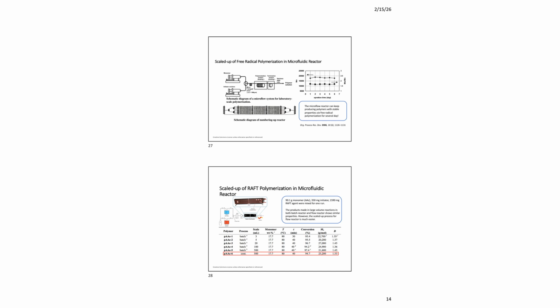This scalability also applies to controlled polymerizations. A scaled-up RAFT polymerization was performed, producing 500 milliliters of polymer solution. When the properties of the polymer made in a small 3 milliliter batch, a large 100 milliliter batch, and the 500 milliliter continuous flow system were compared, the results, conversion, molecular weight, and dispersity, were all very similar. This demonstrates that the excellent control achieved at the microscale can be translated to larger production volumes, and the scaled-up process for the flow reactor is much easier to implement.